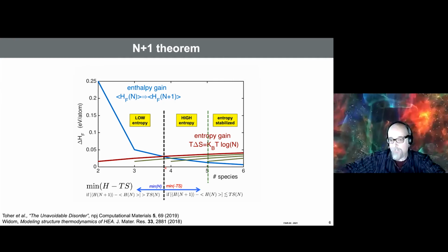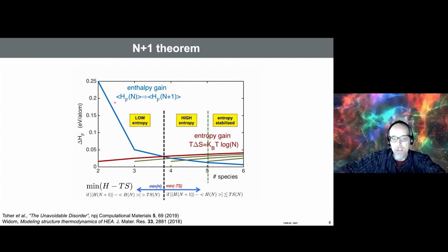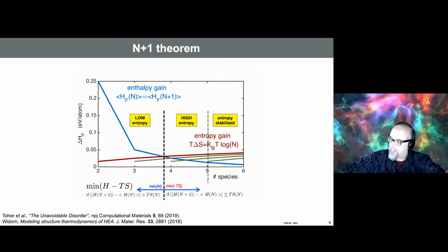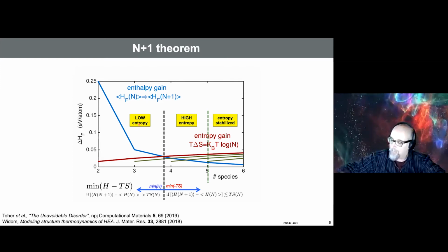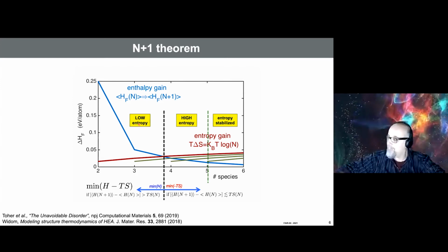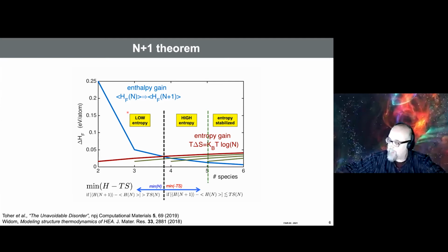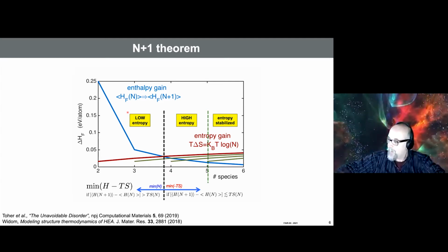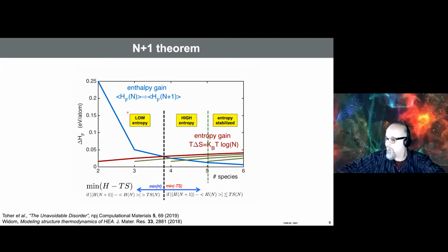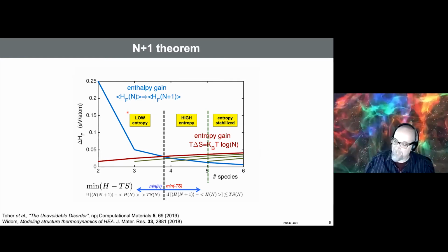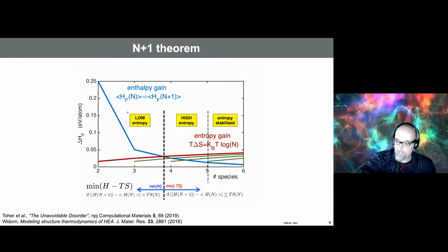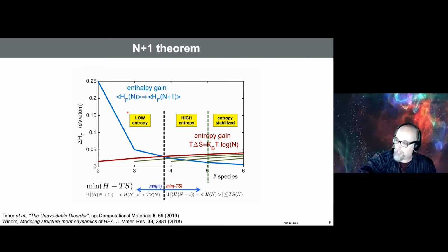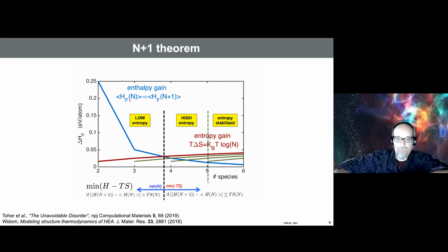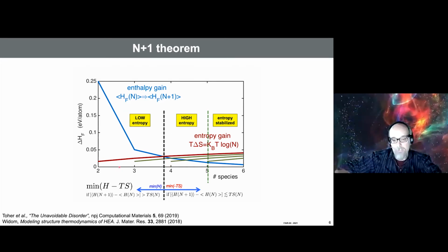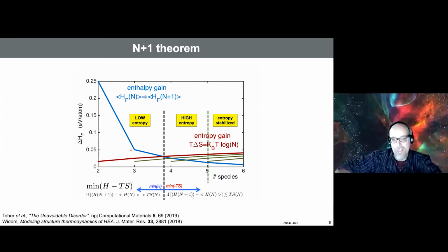If you have a few species, let's say fewer than 4, everything is determined by the enthalpy. So you just minimize the enthalpy on your phase diagrams, and that's what we have been doing for the last 30 years with genetic algorithms, with cluster expansions. We always like to minimize the enthalpy to find the most stable configuration, and it works beautifully. So for a minimum number of species, you just minimize enthalpy.